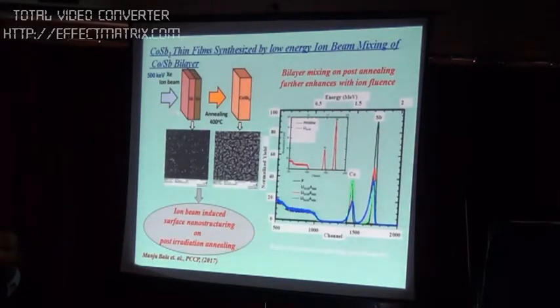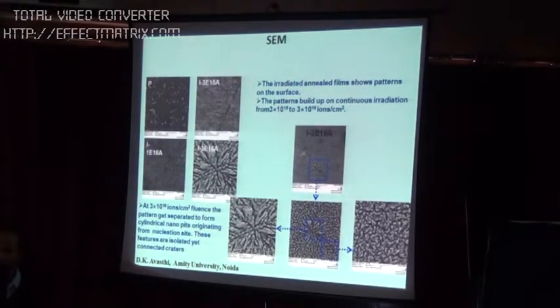And this is the same thing again being seen by a different technique. So you have Co and Sb, and then after irradiation and annealing you get the CoSb3 here completely. And these are the Rutherford backscattering spectra, which show that there has been some mixing at the interface. It shows that only, but the previous slide has shown that there is a phase formation by X-ray diffraction. And again in this case too, you have this flower kind of structure which, when you magnify it further, you see that they are basically nanostructures. So this is the assumption we started with, and we are getting the same thing. So these are very good thermoelectric thin films.